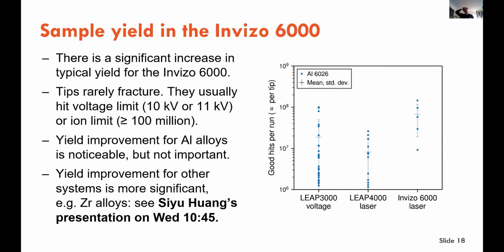The last result I'll talk to is that there is an enormous increase in yields for the Invizo 6000. So the figure on the right shows good hits per run scraped from our Atom Probe databases for all of the 6026 that I've run. And there's a modest increase for the 6000 compared to 3000 voltage, but it's aluminium. It runs really, really well in voltage pulse mode. What we found is that the tips usually hit the voltage limit or the ion limit well and truly before they fracture. Tips basically don't fracture in the Invizo. It's really, really quite cool.